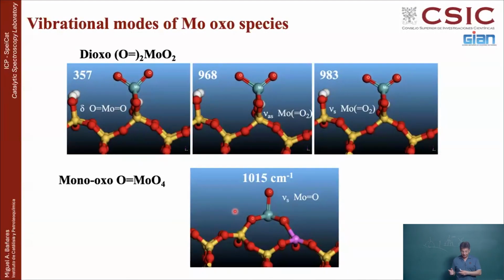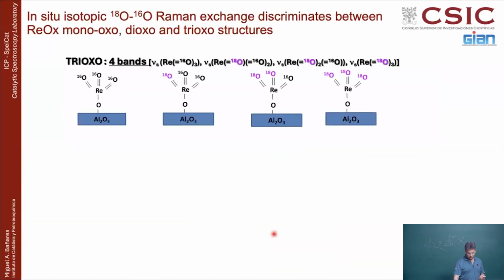And one nice thing that you will find out is that when you compare Raman and infrared, for instance, in this case, if this vibration is stronger in Raman, this is weaker in Raman. But for infrared, it's vice versa. This one will be stronger in infrared and weaker in Raman. So if you see it like this in Raman and like this in infrared, you know you are dealing with dioxo. If you see a given frequency like this one in Raman and exactly the same frequency in infrared, it's because it is just a single band. Sometimes, for instance, maybe one of the modes is so weak that you don't see it, you only see one, but Raman will see one, infrared will see the other. So if there is a difference between Raman and infrared, it will be dioxo. And if they're identical, it will be monooxo. And of course, there are systems like rhenium, which is trioxo. So it has one leg and a trioxo group, because rhenium is heptavalent, it's rhenium 7+.